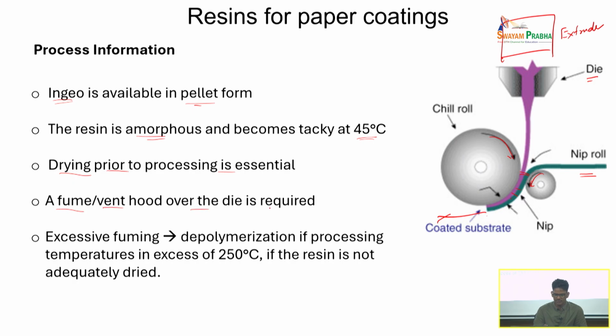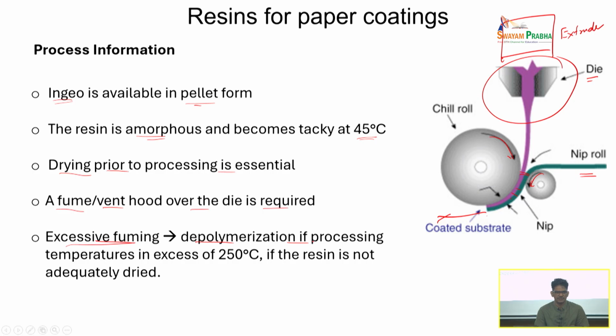Also you need to have something called a fume or vent hood over the die, especially over this place, so that vapor that may come out can be handled. Usually if you do LDPE, you don't need all this. You don't need drying because LDPE doesn't absorb moisture. You don't need a fume hood near the die section because it doesn't give off any vapor. But since this is a biomaterial, it is prone to absorb moisture, and it is prone to release some gases when it processes. Sometimes if you see excessive fuming, it basically means that there is depolymerization.